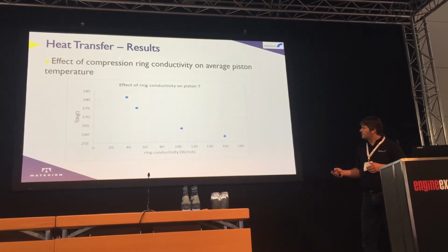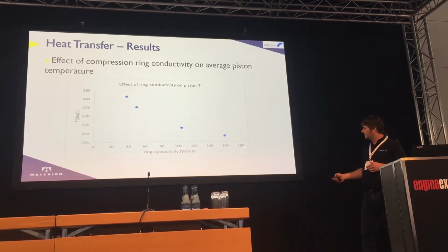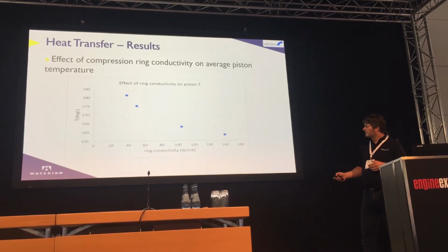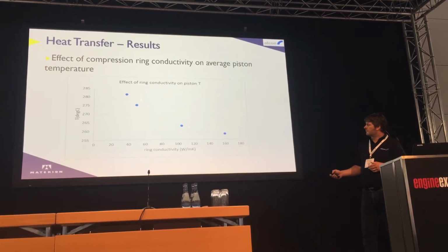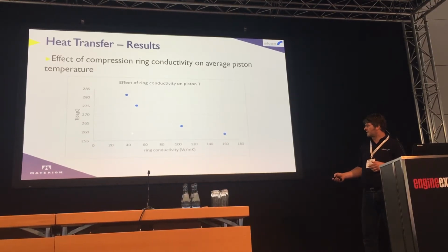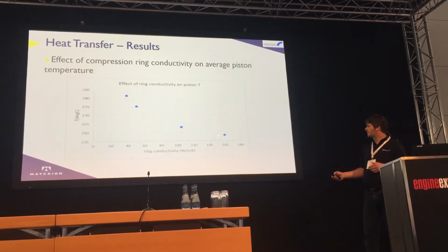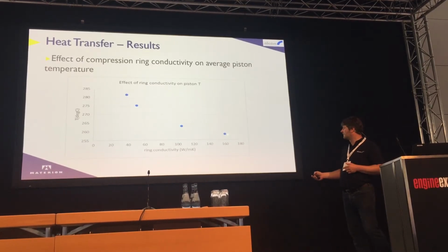So this graph here shows ring conductivity and temperature. So the standard ring is operating around this kind of temperature, and as we increase the ring conductivity, we're reducing the average temperature of the piston significantly, about 10%, by changing the conductivity of the ring.